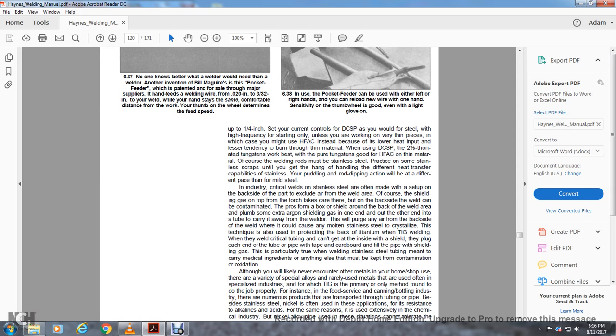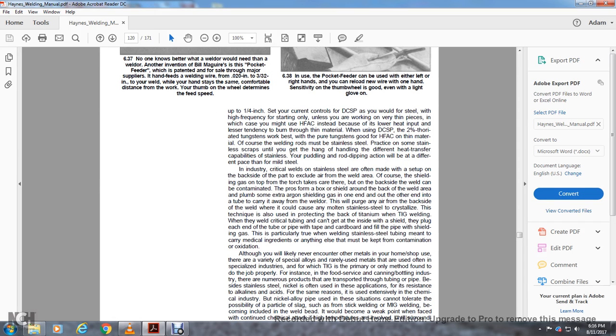Practice on some stainless steel scraps until you get the hang of handling the different heat transfer capabilities. With stainless steel, your puddling and rod dipping action will be a different pace than for mild steel. In industry-critical welds, stainless steel is often welded with the backside of the part set up to exclude air from the weld. Air can contaminate the backside of the weld, so the gap at the top of the torch carries shielding gas and puts it on the backside.